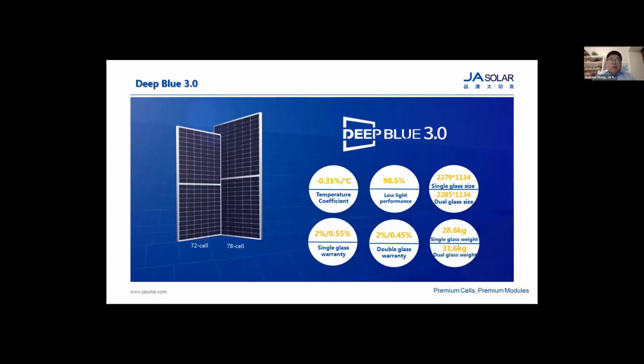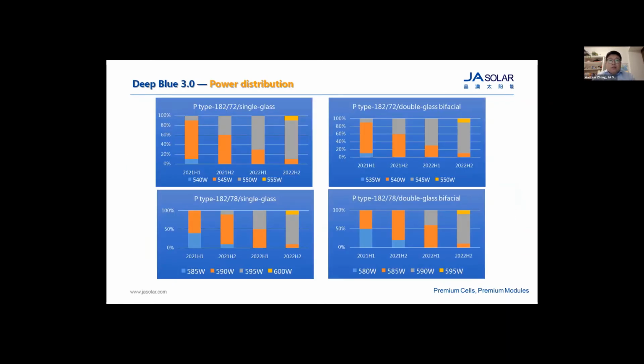So here we would like to share a summary of the DeepBlue 3.0 solar module benefits. Currently, this type of module is available to order already, with annual production capacity around 20 gigawatts in 2021. It has a lower temperature coefficient of around minus 0.35% per centigrade, high efficiency low light condition response, and excellent degradation, for monofacial and bifacial. So this is the power distribution. We are focusing on the 72 cells 182 millimeter module and the 78 cells 182 millimeter module within 2021 and 2022.